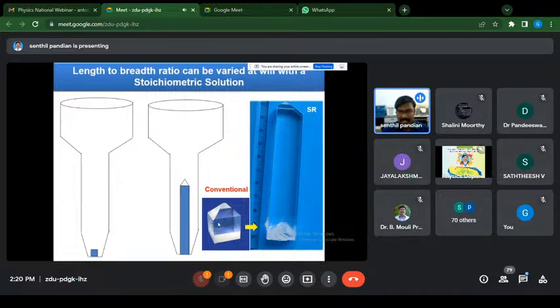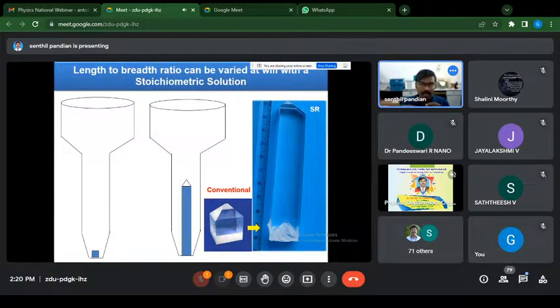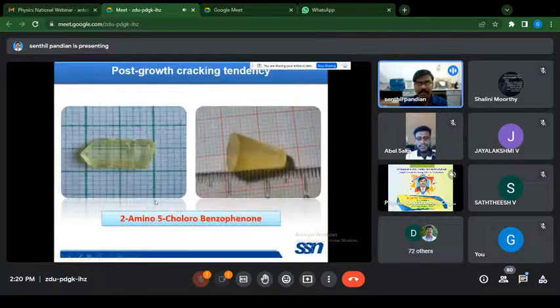Normally the phase, plane and the growth direction would be like this. But here in the SR method, depending upon the pH of the solution, one can increase or decrease the growth direction of any crystal. So this is for the KDP crystal. If it is a new material, you have to optimize yourself with a different pH, a different solvent, a different material. This is a pencil shaped KDP single crystal grown by this SR method.